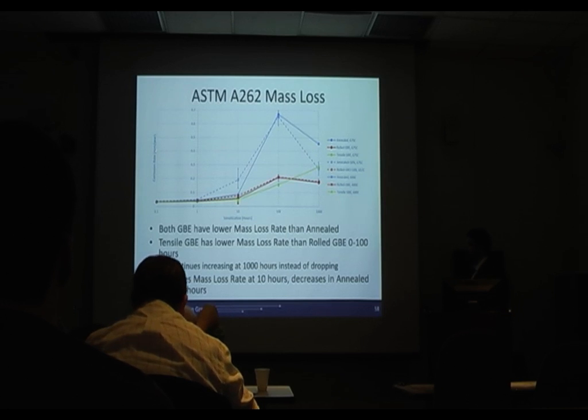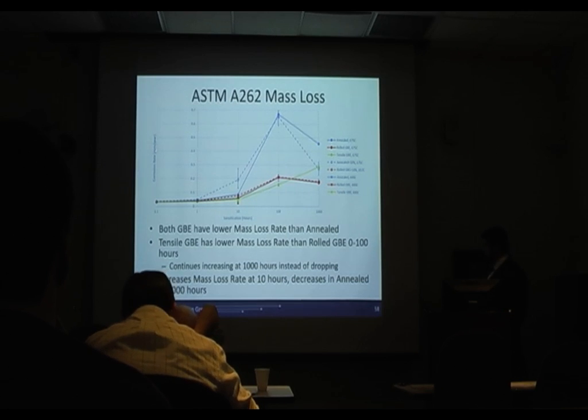And then things get even more interesting at 1,000 hours, because all the conditions drop in mass loss, indicating that desensitization has set in, except for the tensile GBE, which has continued to increase.